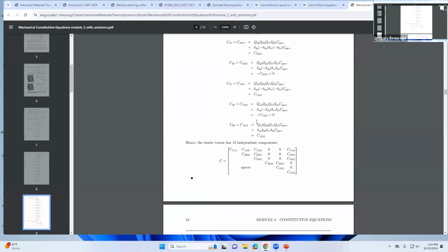So you're pulling it in the Y direction, and you're looking at the gradient in the X direction, or the other way around. You're pulling it in the X direction, and you're getting the gradient in the Y direction. So it's like you move a deck of cards. You're drawing something out, but the direction you're looking at the gradient is normal to the way it's changing. So the normal to the thing is up, and the force you're putting on it is horizontal. That's the C66 in this context. All the other ones are oddball things that are happening, like when you extrude it, it swells laterally.